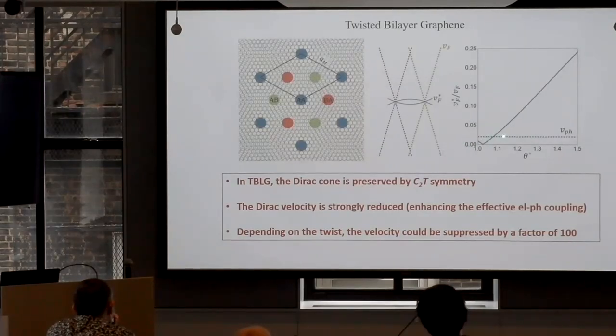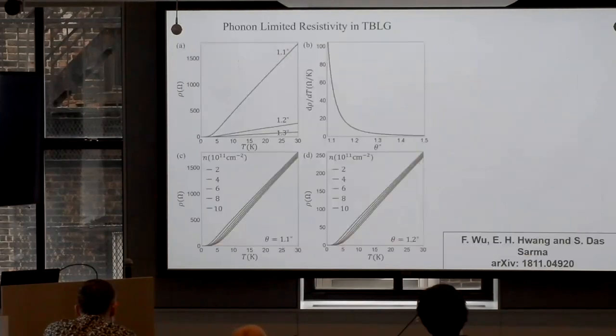So I will do a theory which would not be valid over here because Migdal's approximation will fail when the velocity is lower. But I have a theory which is reasonable over here. Monolayer graphene is somewhere up here, okay? Way up, like 5 degrees or something. And there are all these symmetries that we're taking, I'll come to symmetry later on. Depending on the twist, the velocity could be suppressed by a factor of 100. This is the important thing you need to remember.